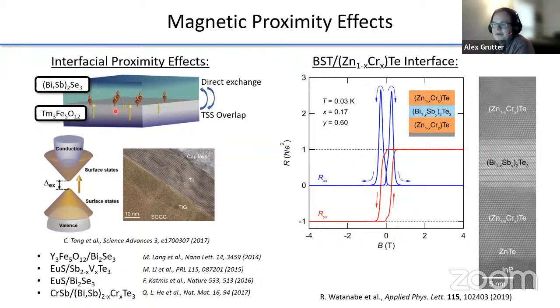a thin film heterostructure so that there's an interface between this large reservoir of magnetic order and the topological insulator itself. And then through a combination of direct exchange or overlap and charge leakage, you can actually get a magnetic spin polarization to be induced in the topological insulator at the interface. And this also will effectively induce a gap in the surface states.